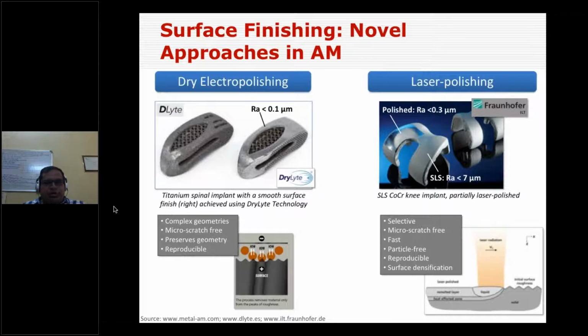So there are some novel approaches in enhancing the surface finish or super finish. Under that you have dry electro polishing, where we can see an RA value which is less than 0.1. Normally, as built, you may typically get around 10 to 15 RA, or at max 7 RA. That is the maximum you can get as far as my knowledge goes. But my 10 or 15 RA value has improved to 0.1 RA value through this dry electro polishing or laser polishing from Fraunhofer.